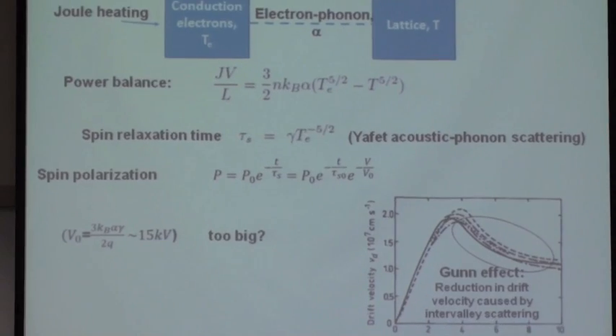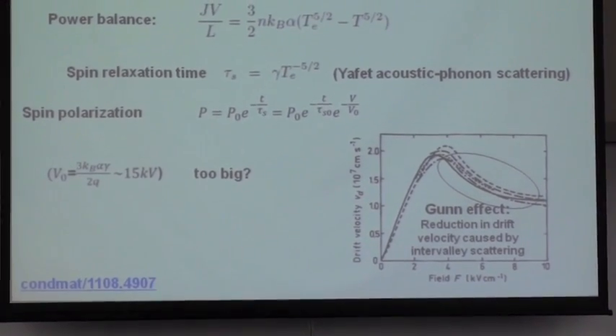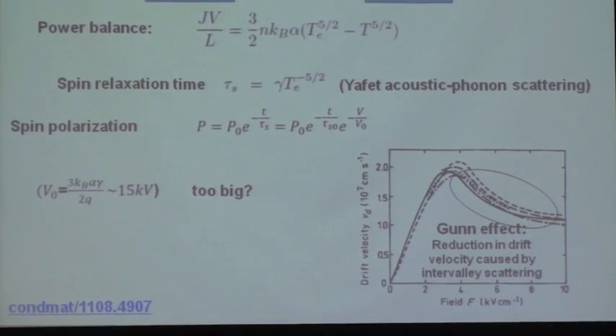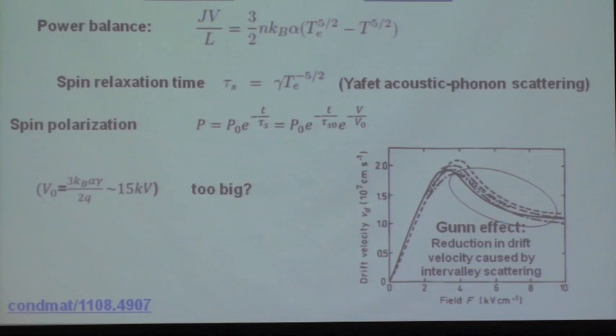Now, if I make an analogy to charge transport, this would be like a spin Gunn effect. The Gunn effect in charge transport in semiconductors is this counterintuitive reduction in drift velocity upon the application of large electric fields. What happens at low electric fields is everything behaves ohmically. We start increasing the electric field, and electrons just move proportionately faster with a fixed mobility. But after a certain point, in the Gunn effect case, you heat up these electrons. They move into secondary conduction band valleys, and they lose their kinetic energy, and so the electrons actually slow down. So this is a negative differential mobility. What I'm talking about here is a negative differential spin lifetime, where by increasing the electric field and getting a shorter transit time, you actually depolarize your electrons instead of retaining the spin polarization.